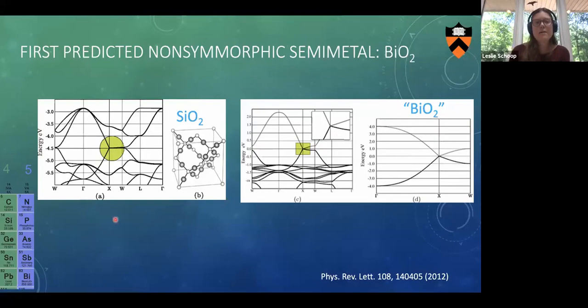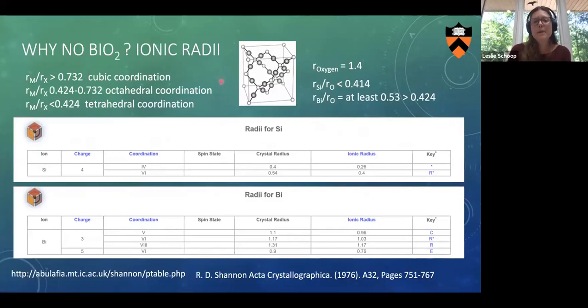One is that, as I said several times, unfilled shells and P systems are usually not stable. This is also a problem here, but I'm not going to focus on it. I'm just going to give you an example of why you cannot just put a gigantic cation like bismuth, which is a lot larger, into a space which was filled by a tiny cation like silicon. So let's look at the ionic radii. You can go to this very beautiful website, where all the Shannon ionic radii and crystal radii are tabulated. You can look up the radius of your anion oxygen, it's 1.4.